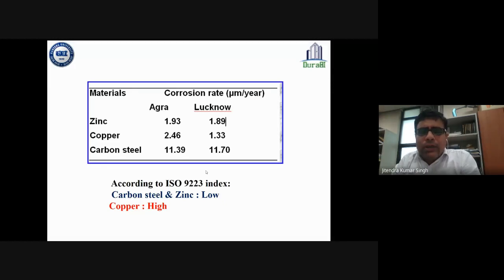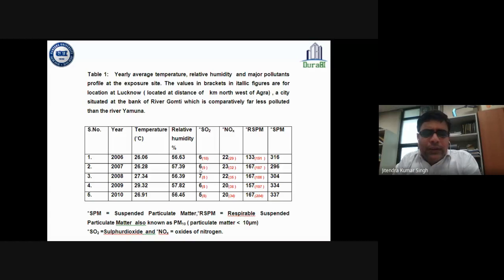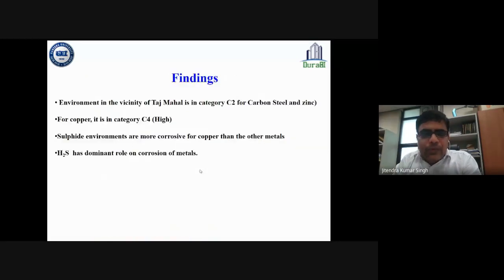You can see according to ISO 9223 index, carbon steel and zinc have a low corrosion rate, in the low condition, and the copper is very high. You can see copper for Agra showing 2.46, while the carbon steel for Agra and Lucknow is around 11.39, 11.70, and zinc is also around 2. So it is not so expensive. We have exposed different exposures, and we have calculated and gathered the meteorological data. These are the contents. So, findings.